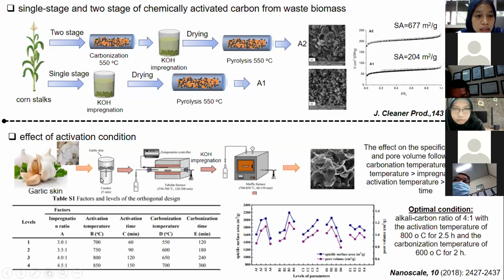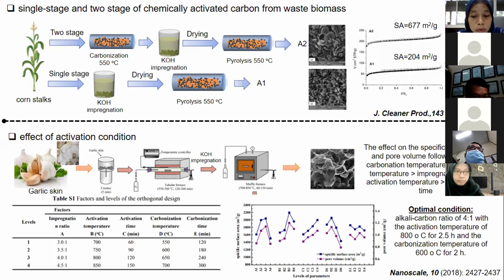And the next is about other parameters in the chemical activation process. Zhang et al. reported the chemical activation process on garlic skin using KOH as activator agent. They investigated the effect of alkali carbon ratio, activation temperature, activation time, carbonization temperature, and also carbonization time on the specific surface area and pore volume. This is the method to obtain the activated carbon.